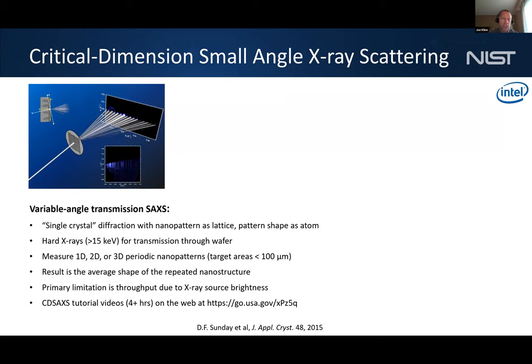And so CD-SAX is essentially a variable angle transmission SAX. And so we have the X-rays hit the wafer and you measure some sort of grating structure. And then we go through the wafer and look at the scattering pattern as a function of angle. And since we have this grating pattern, it's essentially single crystal diffraction where the nano pattern is the lattice. And then the pattern shape is essentially like your atom, or like the protein if you're doing protein crystallography. And since we go through the wafer for classic CD-SAX, it's always greater than 15 keV so that you minimize the absorption.